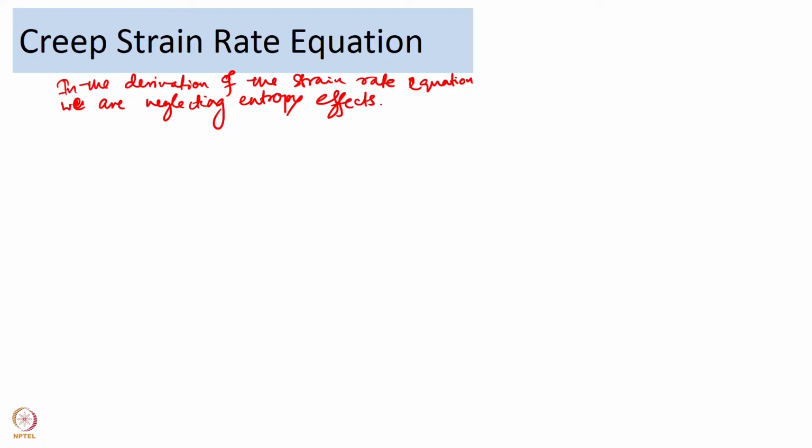So, we are talking about point 1 and point A and point C, and we said they are at a low energy configuration, both A and C. So, when the dislocation moves from A to C, we are talking about a free energy change, and generally when we talk of free energy change, we say delta G, and delta G is delta H minus T delta S.